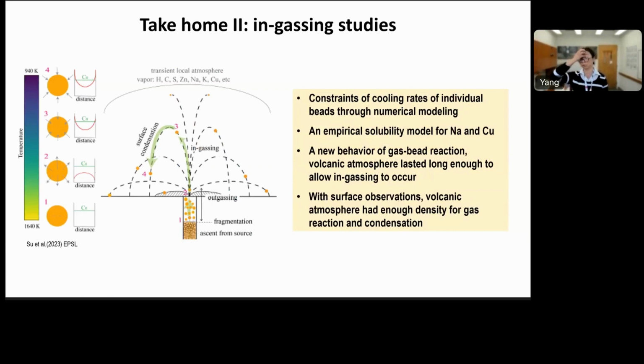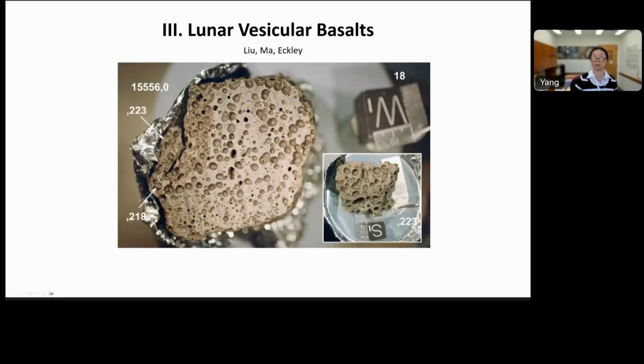So here is take home 2. From the individual bead concentration profile study, we can constrain the cooling rate of each bead. We also can generate empirical equations for sodium and copper solubility. We only model sodium and copper because we only have diffusivities for those two elements. This is a new behavior that has not been recognized before. Together with our surface observation, we think the volcanic gas has enough time and also enough density to allow those behaviors to occur. So that's our second part of the volcanic beads.